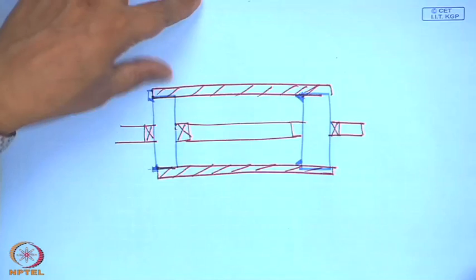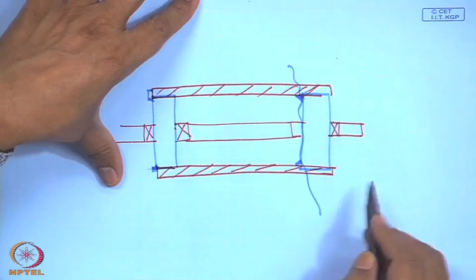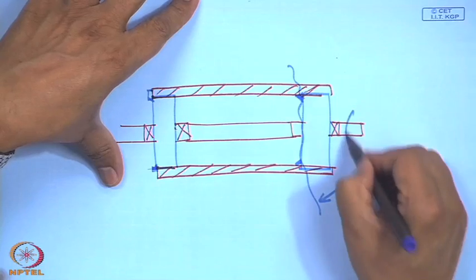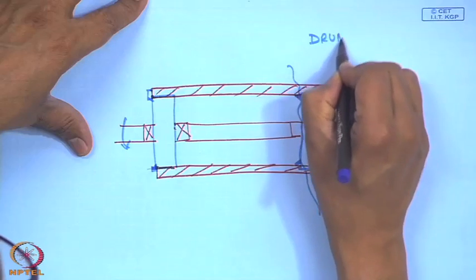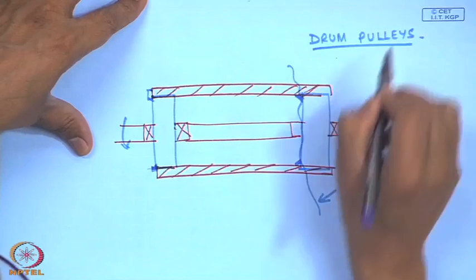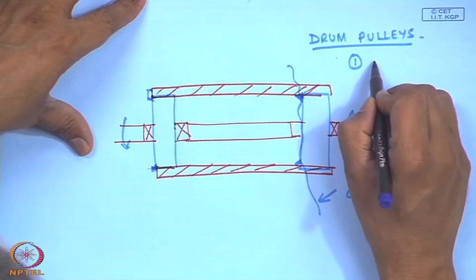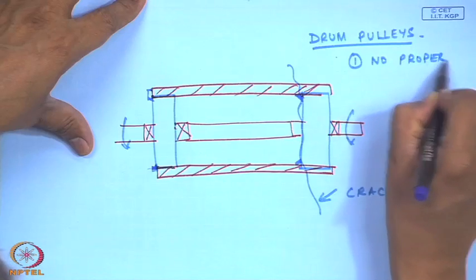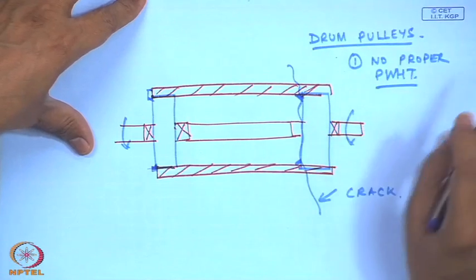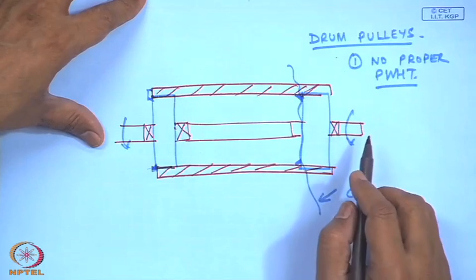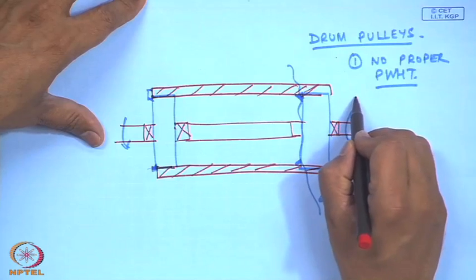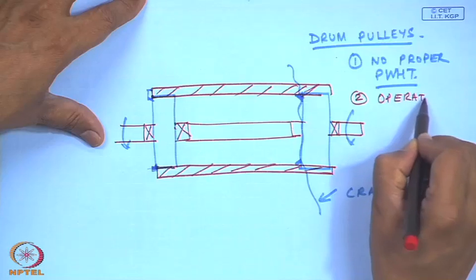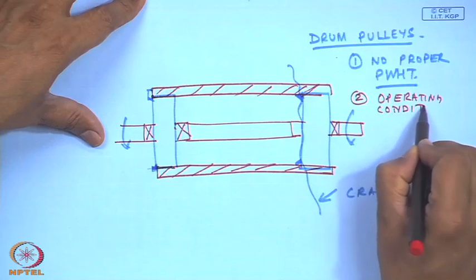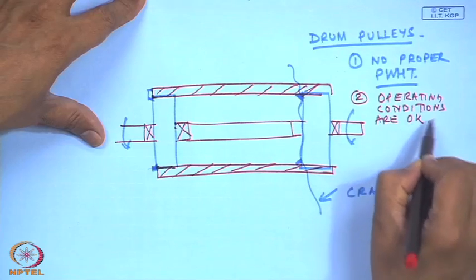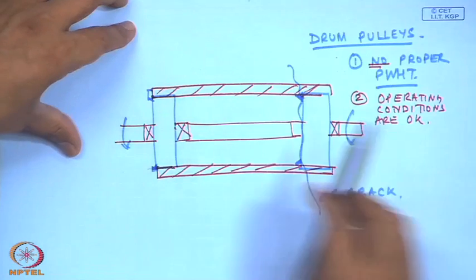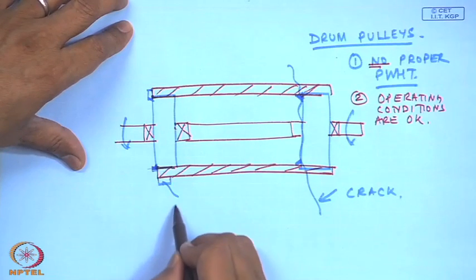There have been cases where we have seen that these materials fail. A crack occurred in such pulleys, they are known as drum pulleys. Okay. And this is because of a couple of reasons, because no proper post weld heat treatment was done, and so this kind of failure is not because of the operating conditions. Operating conditions are good enough. Okay, but because of no proper heat treatment. And in such cases, they recommend that a UT inspection is done.